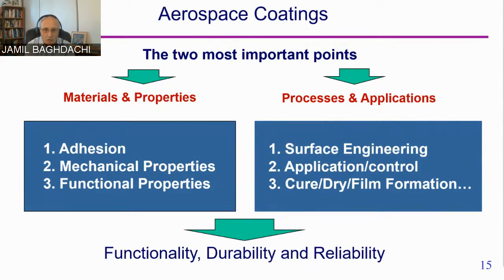That paint is not going to last, because when it goes up very, very high and cold, it's going to begin cracking. And when water goes on it, with an enormous amount of rain or humidity, or maybe at the base, for example, at 110 degrees or so, gradually that goes bad. And then the functional properties of the coating. Second, if you look at the right side, surface engineering.